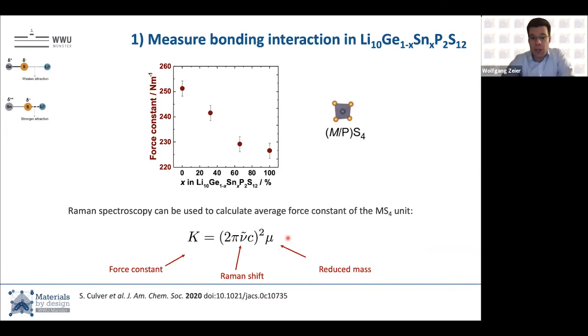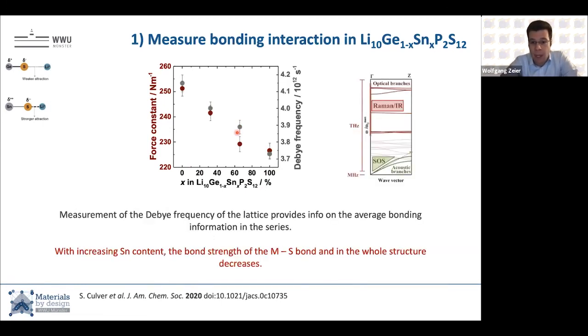If you weigh this via the contributions that we have in there, germanium on the left, tin on the right, we see that the force constant of this tetrahedron decreases. So this chemical idea that the bond becomes weaker if we move from germanium to tin seems to be the case, at least based on the Raman data. We can also measure Debye frequencies, which are an average metric of how stiff and how strong bonding interactions are in the whole solid, and they also decrease. So overall, if we put tin into the system, the bond strength of this metal-sulfur bond and the whole structure decreases.